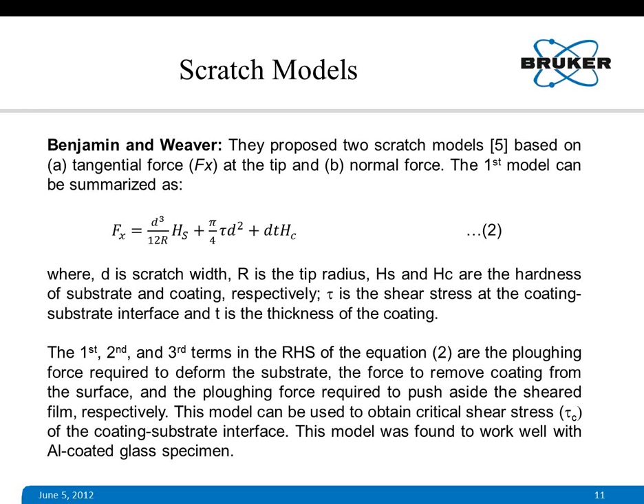There are three terms in equation 2. The first term denotes the plowing force required to deform the substrate, and the second and third terms denote the force to remove coating from the surface and the plowing force required to put aside the sheared film, respectively. If we find Fx, and Hs and Hc are known, thickness of the coating t is known, and if we find the scratch width D, we can find the critical shear stress at the point of failure. That critical stress could be used for comparing several coated specimens. This particular model worked well for metal coated on glass specimens, especially aluminum, but it doesn't work for some other coating systems.